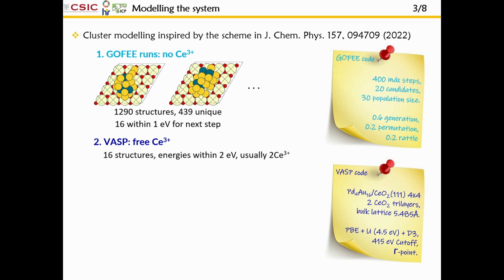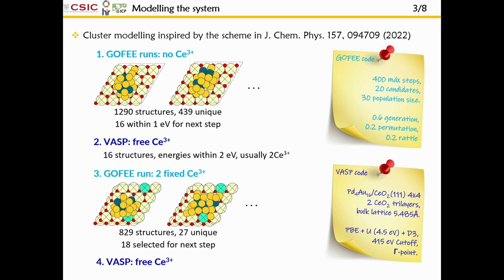So the idea is that using GOFEE, you can explore many more structures than you would do using only DFT. But it has a problem, and it is that it doesn't treat electrons. So when you put metal nanoparticles on ceria, the metal nanoparticle gets oxidized and electrons go to the support. And so cerium 4+ atoms from the ceria become cerium 3+. And you do not have that here. You can put them, but you have to select them manually beforehand. So you need to do subsequent runs of different GOFEE runs and VASP optimizations to obtain your final model.